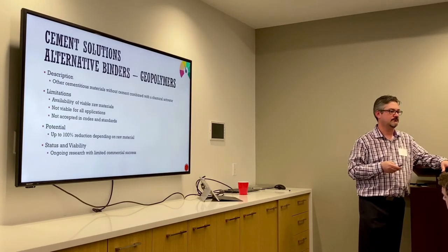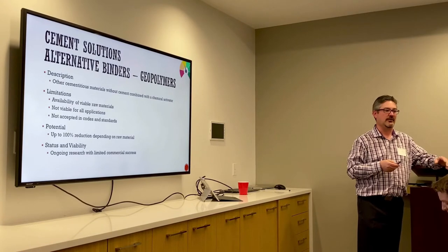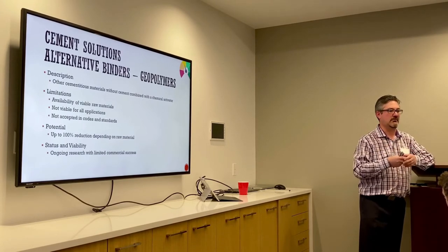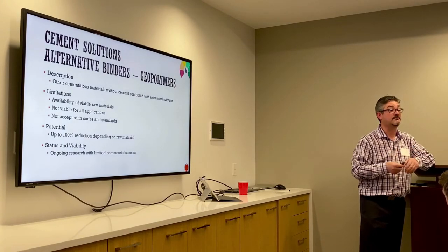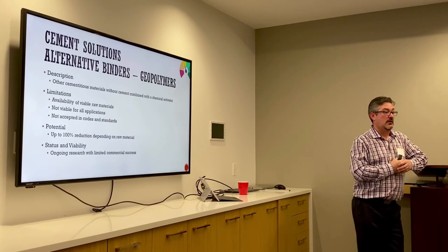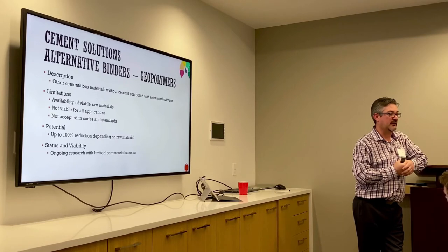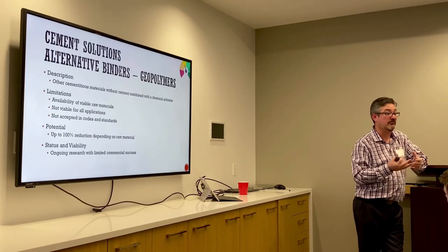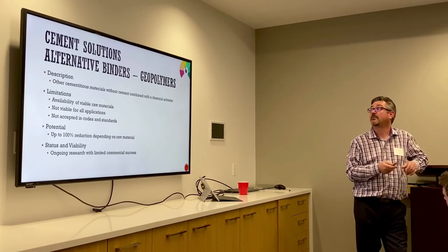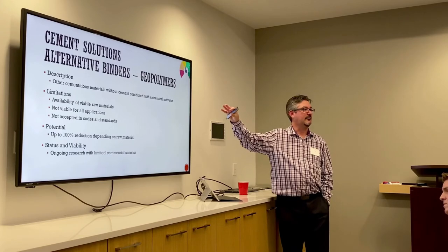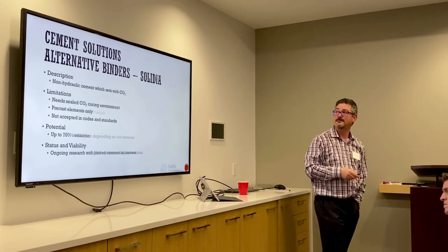Does this affect the strength of the concrete? Yes. Depending on what the material is, what the binder is, and all of that sort of stuff, you may not be able to use it for high strength concrete, for example. It may have some very limited applications. What kind of applications would something like this have? Like a concrete that has this in it? It's being used in paving stone manufacturing and things like that. Nothing structural for the most part. Some roads, sidewalks, and so on and so forth. So I rate this at a 3. Again, not entirely suitable for how we use cement today.